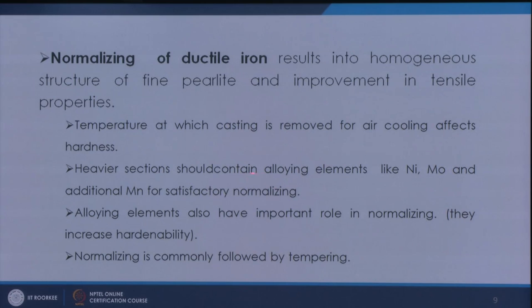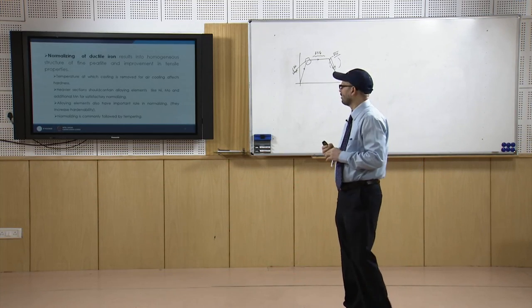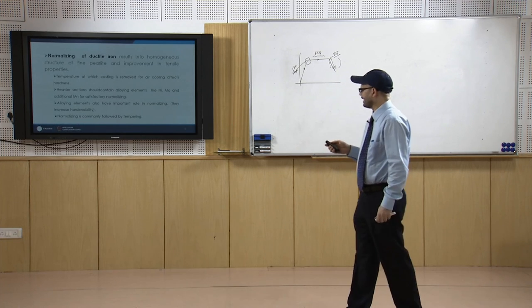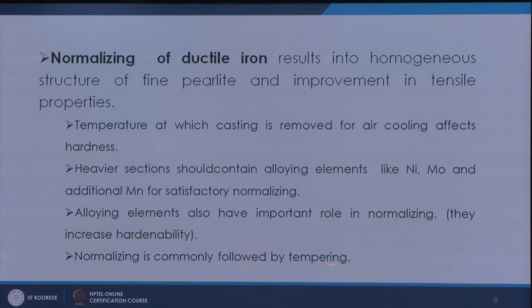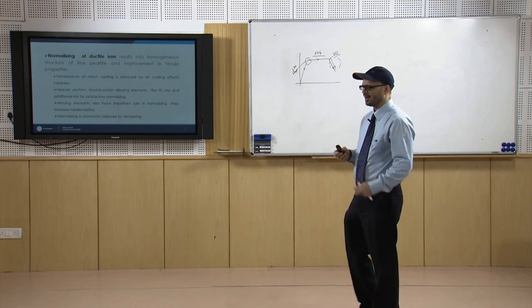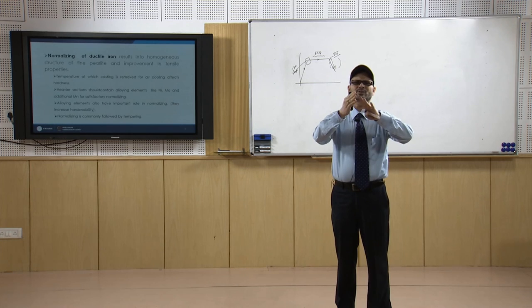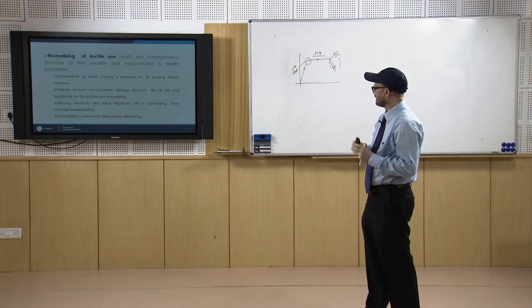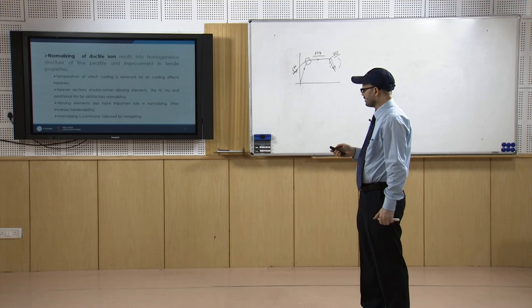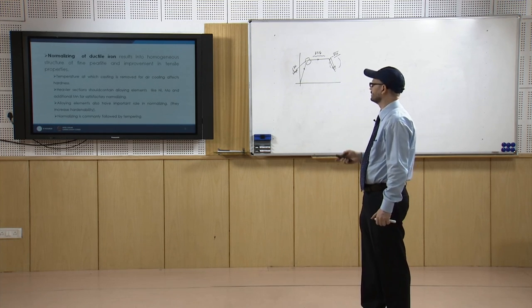Heavier sections should contain alloying elements like nickel, molybdenum and additional manganese for satisfactory normalizing. That is one of the conditions that you should have these alloying elements. They have an important role in normalizing because they enhance the hardenability of the material. And normalizing is normally followed by tempering. Tempering will be done at a temperature of maybe 200 to 400 degree centigrade, holding for some time and then cooling. That will be essential once we go for the normalizing treatment.